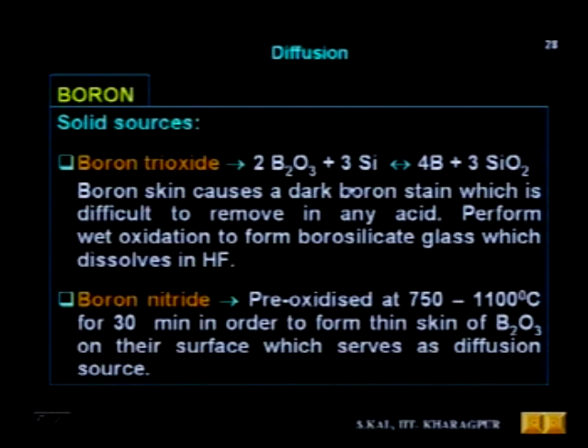Next one is boron nitride. That is also a solid boron source. Boron nitride wafers or cakes are available from different companies and suppliers, and they are named BN 975, BN 950, BN 1100, etc. These boron nitride cakes are pre-oxidized at 750 to 1100 degrees centigrade for 30 minutes in order to form a thin skin of B2O3 on their surface, which serves as the diffusion source.